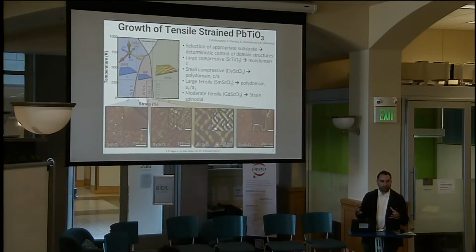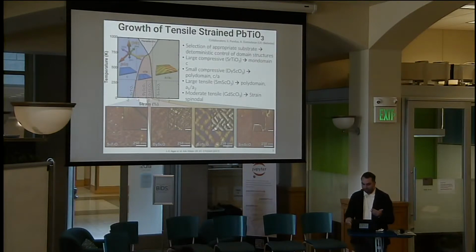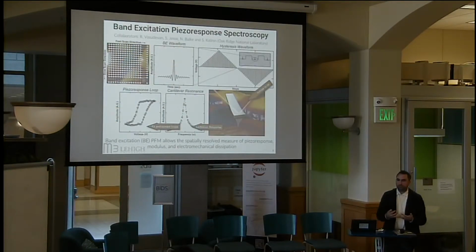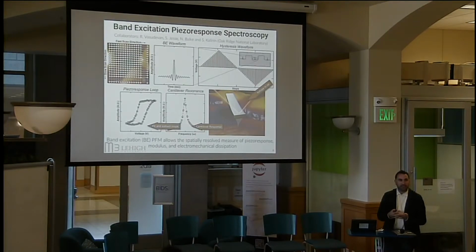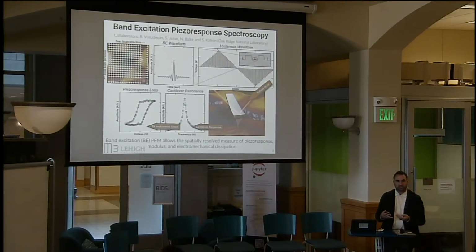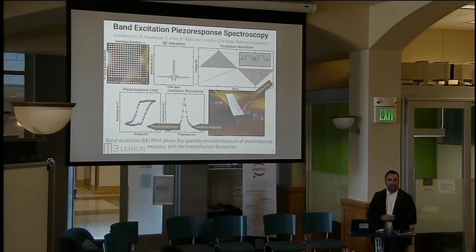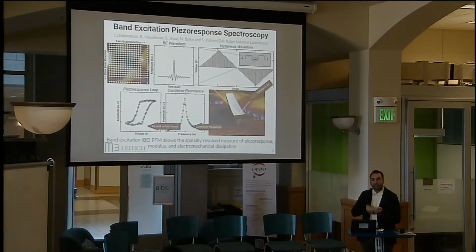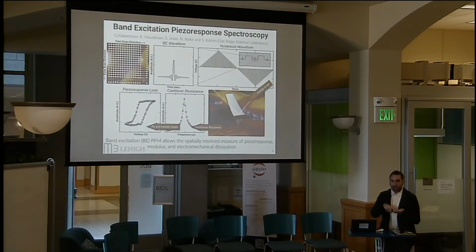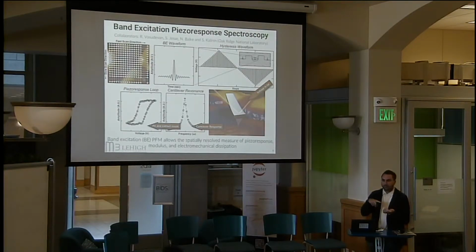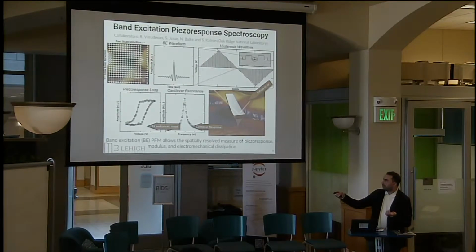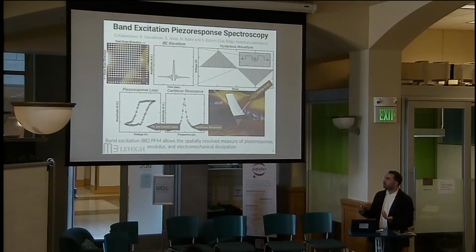But as the material gets more complicated, there's a range of interesting coupled responses that are hard to understand. To characterize these materials, we relied on a technique called band excitation piezoresponse force microscopy, built out of Oak Ridge National Lab. This is an atomic force microscopy technique, so you can think of it as taking a nanometer-scale probe and physically touching it to your surface. That allows you to measure the topography, but you can also use it to perturb the material, applying an electric field to drive transformations, and measure the response of the material.